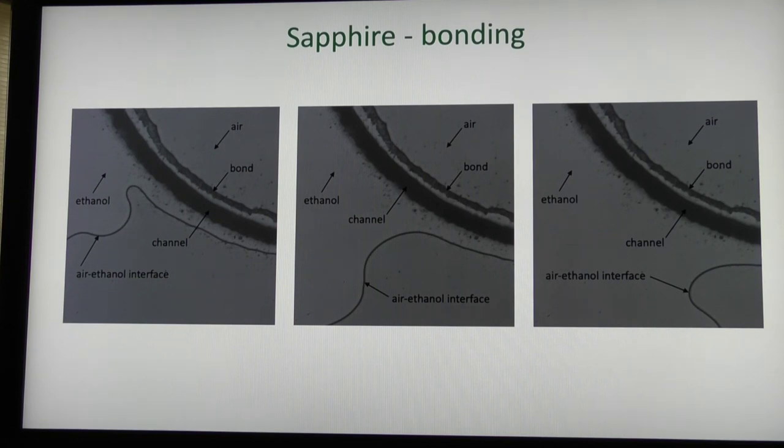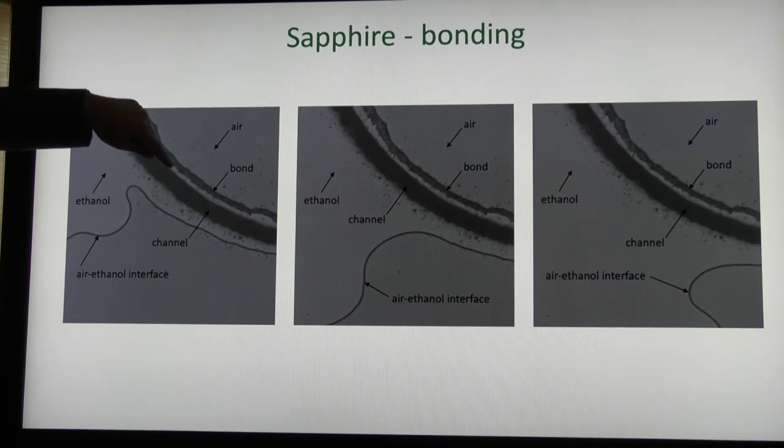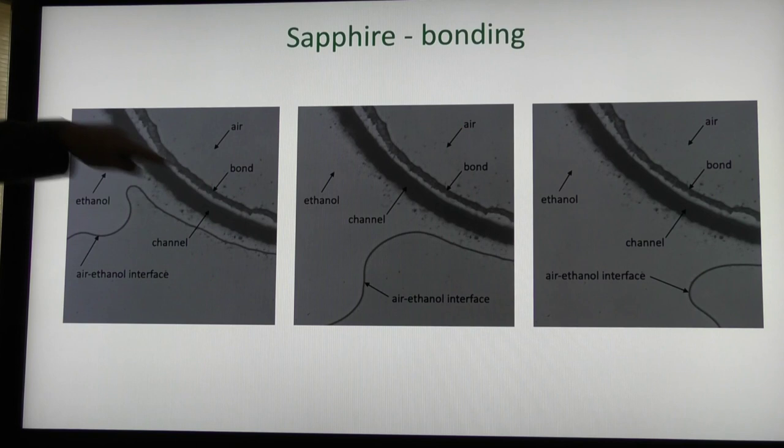So we decided to experiment with the femtosecond laser pulse, to see if a less sharply focused laser pulse pointed at the interface, at the plane where the two sapphire plates meet, would cause the two plates to bond. And we had success, and that's what this is. Instead of etching, by changing the focus of the laser, it bonds the two plates of sapphire that are in contact. And this is due to the movement of the stage with respect to the laser source. They just move along this path and create a bond.